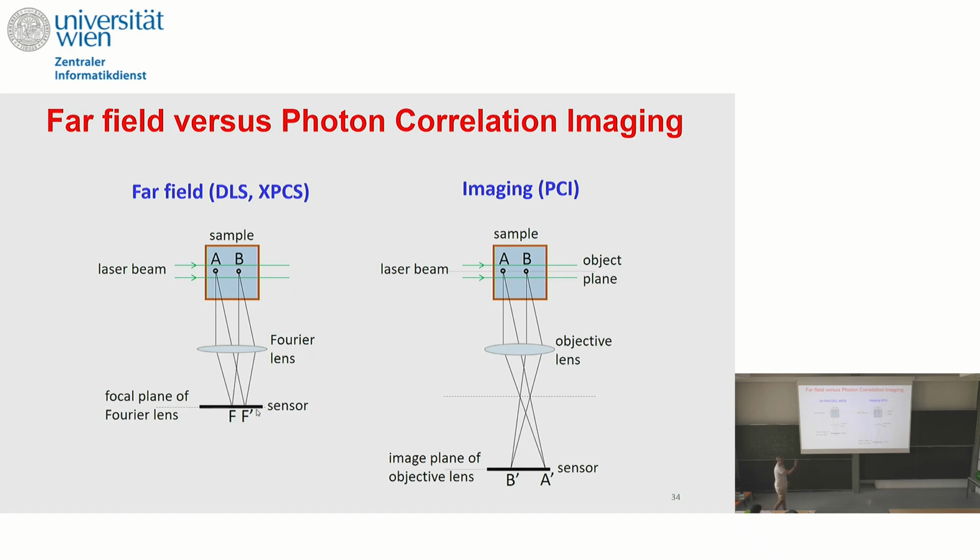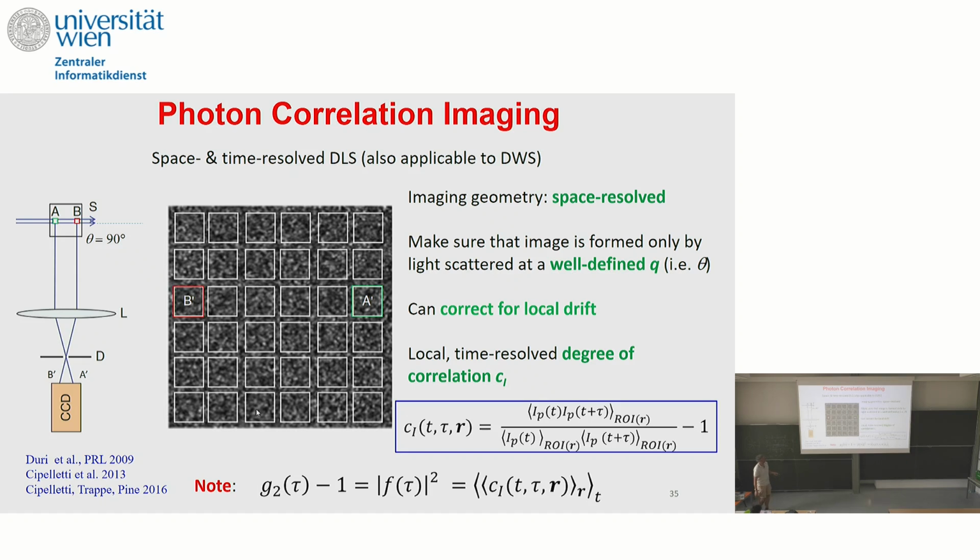So if I look at my speckle image, I can say, aha, I see speckles fluctuating a lot here and much less there. And that's because my sample has more dynamics here and much less there. For example, because it's heterogeneous or because I have a localized rearrangement event here and there. So let me show you how this works. We have this imaging geometry.